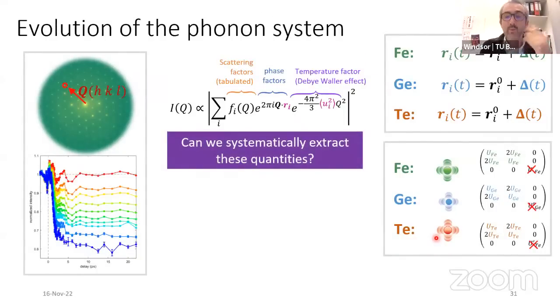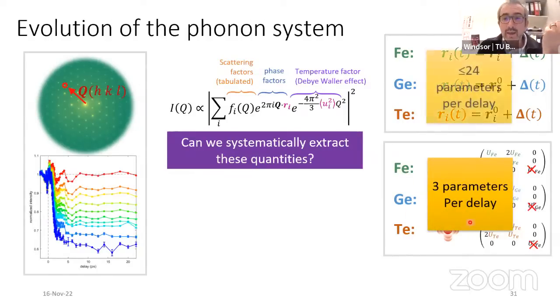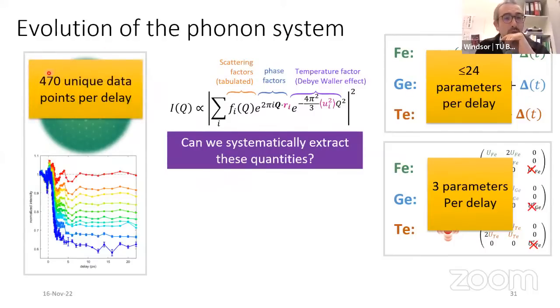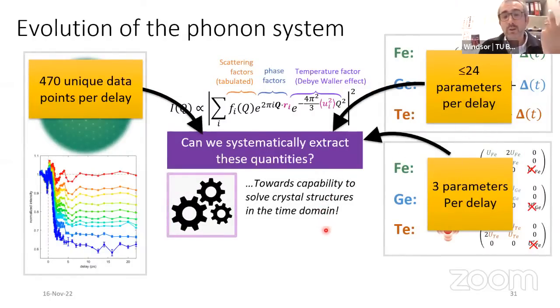The reason it's convenient is because we can have very few parameters. So we ask ourselves, can we systematically extract these quantities from our data? And if we have only 3 parameters describing the incoherent oscillations, and probably less than 24, which is because these are vectors per delay, we could imagine that we have 470 unique data points per delay, which is every one of these Bragg spots. So every one of these Bragg spots is described by a unique equation, which depends on only a few parameters. So we can imagine a situation where we can essentially solve the crystal structure in the time domain per delay. If we have hundreds of data points and only 10, 20, 30 parameters, we can systematically describe all of the atomic motions in the unit cell.